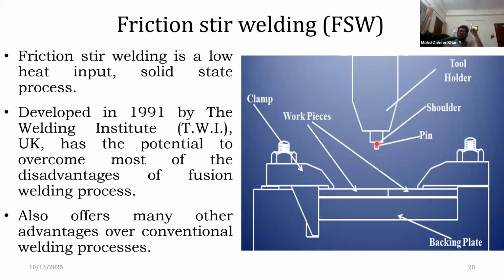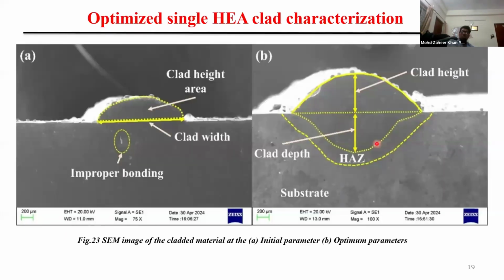Now, laser cladding is again a fusion based technique for deposition, and this has an inherent problem. Whenever I am depositing a layer of clad material on the substrate material, it is essential that some amount of substrate material should also melt. If the substrate material does not melt, as you can see in this left hand figure, then the clad material will not be firmly anchored or joined with the substrate material. And with the application of force, this clad layer will simply peel off.